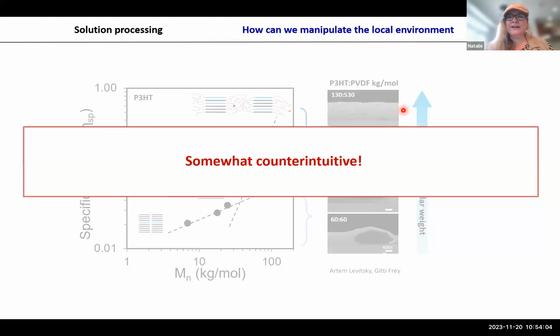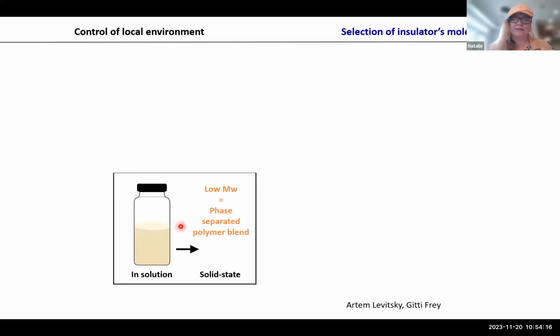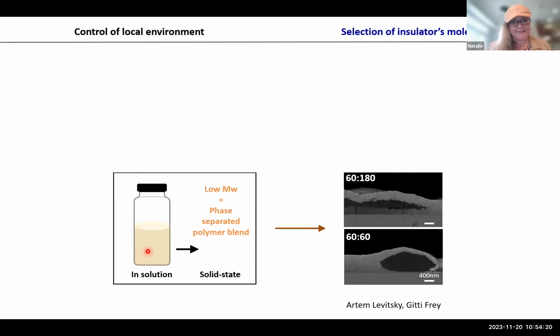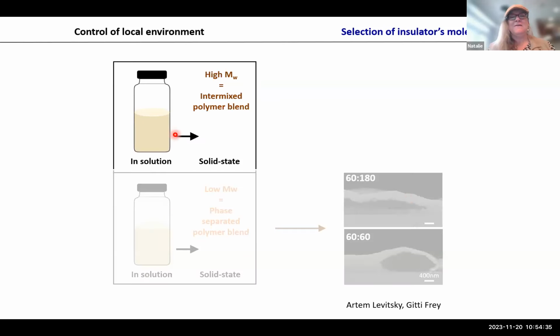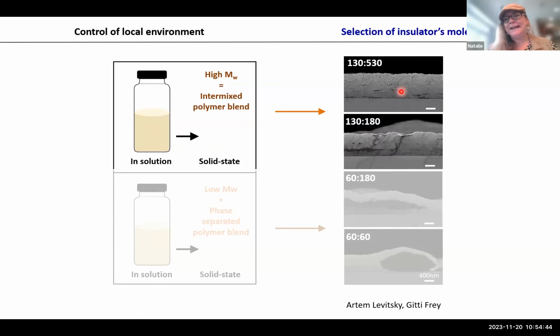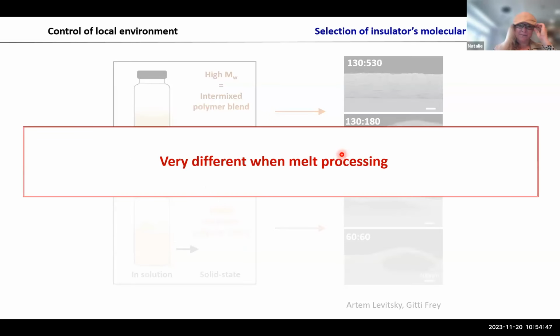If people come from the polymer area, the first thing you think is this is counterintuitive, because usually people say the higher the molecular weight of polymers, the more they phase separate. But the thing is we process from solution. In case you have low molecular weights, they're like little macaroni sticks, not intertwined with each other. So high mass transport, and the high mass transport leads to phase separation. Once you have, imagine here, cooked spaghetti of two colors, they really have a lot of knots. And then you get this nice intermixing.